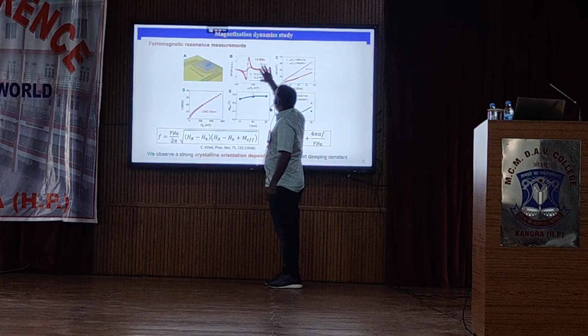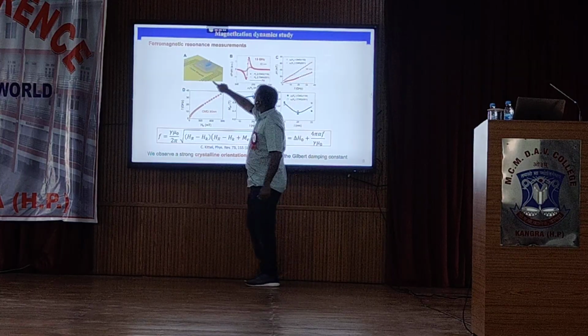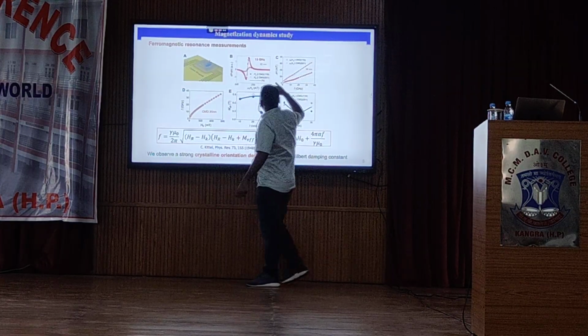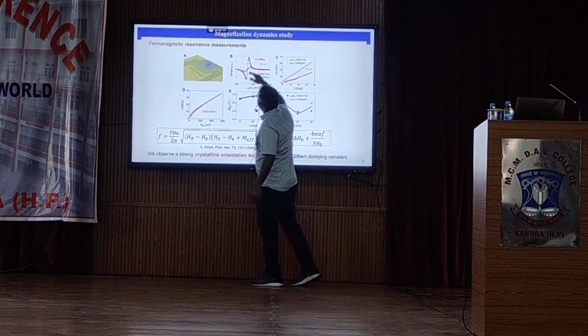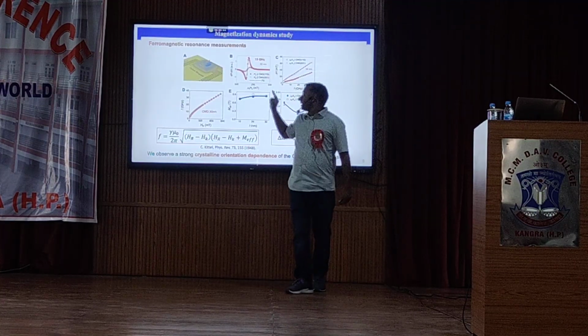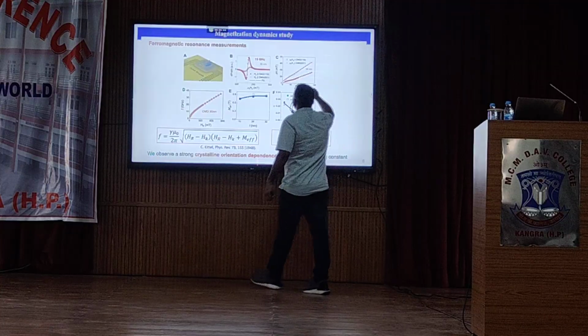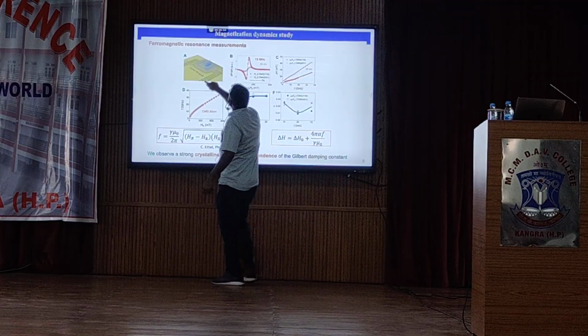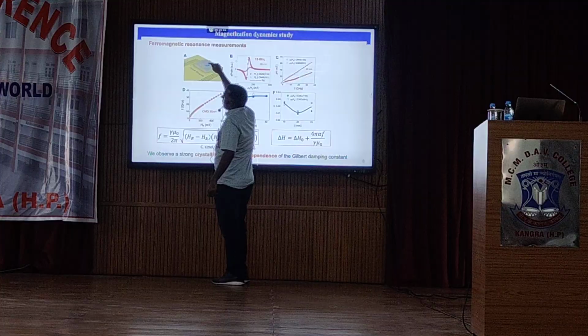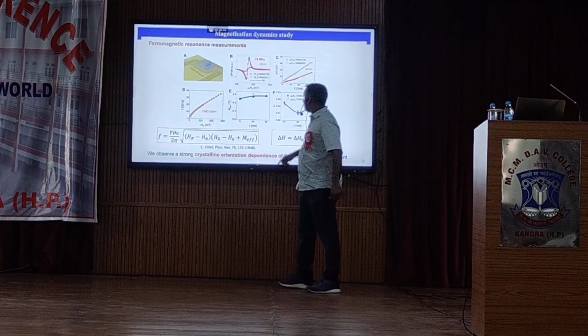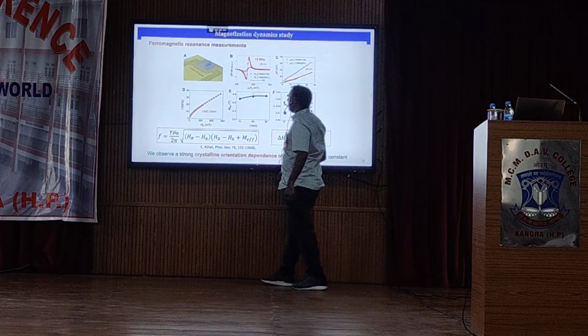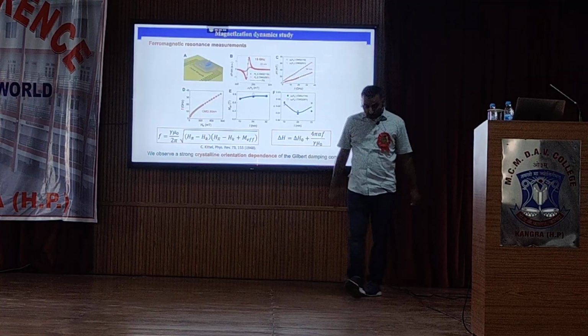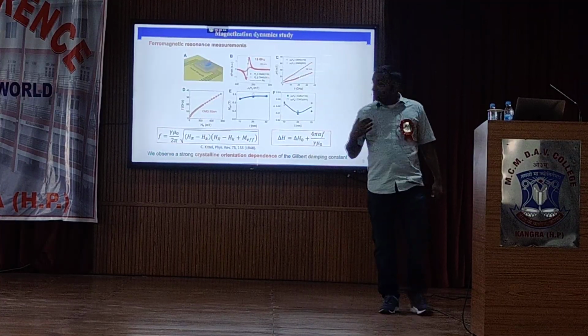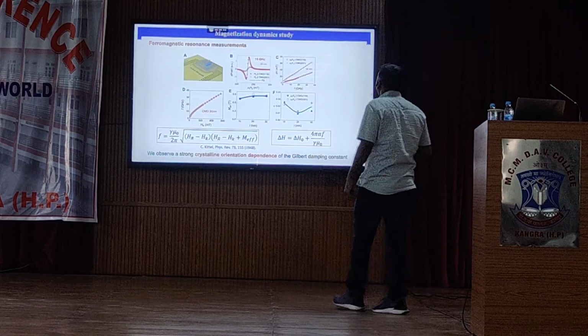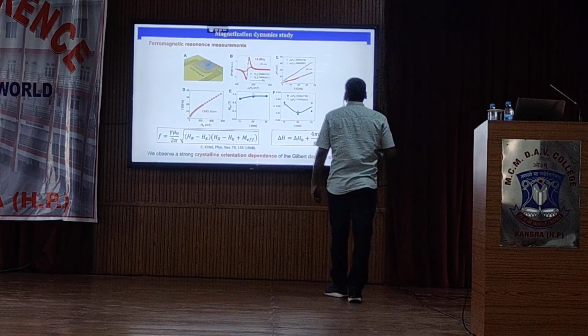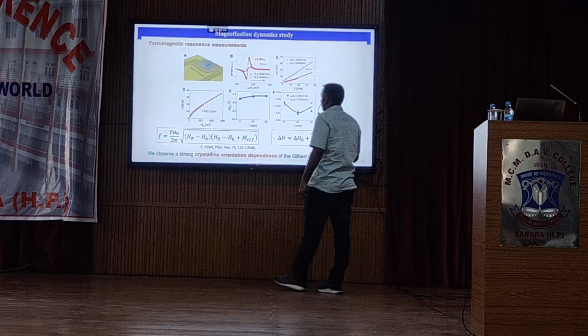I have shown the data for 15 gigahertz of frequency. When we apply 15 gigahertz, while we are sweeping the magnetic field, we look for the resonance condition. So the data for 15 gigahertz is shown here. Whenever there is a resonance between this microwave signal and the rotational frequency of the magnetization, we see this kind of feature. We perform these ferromagnetic resonance measurements in a frequency range of 2 to 40 gigahertz, and the results are summarized here.